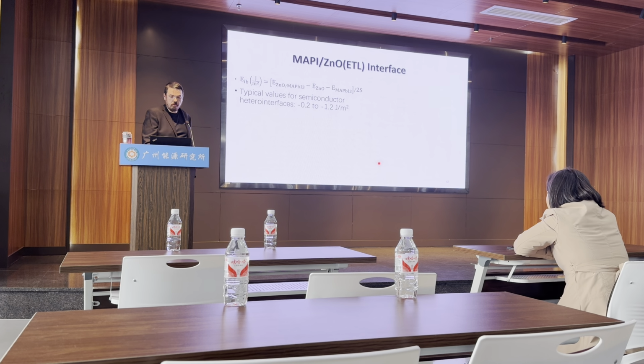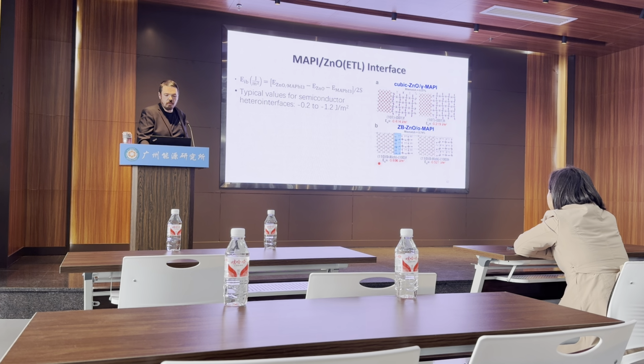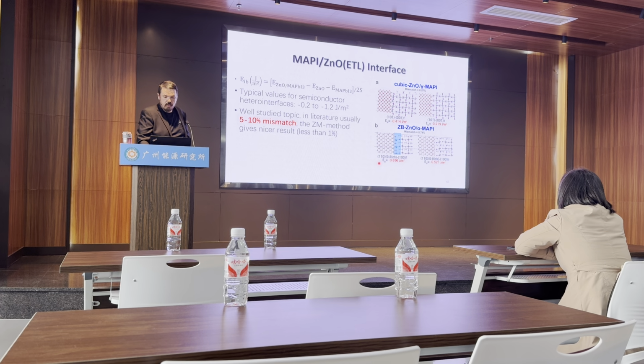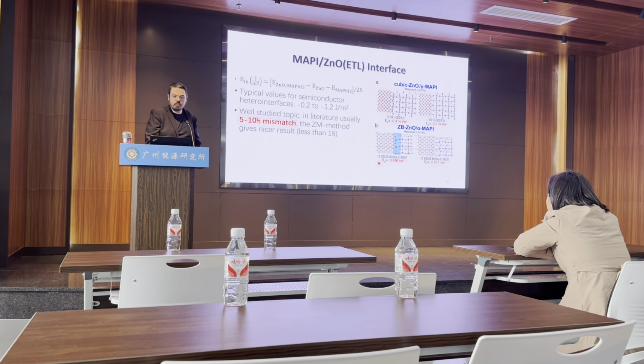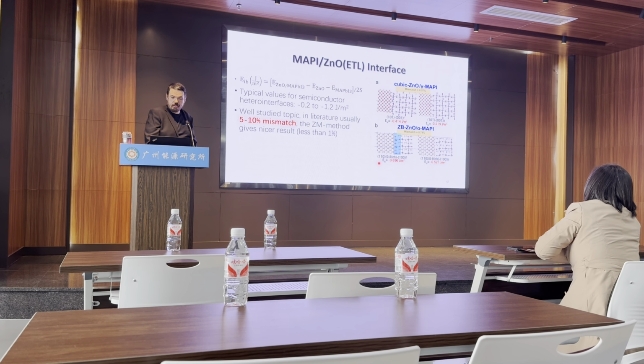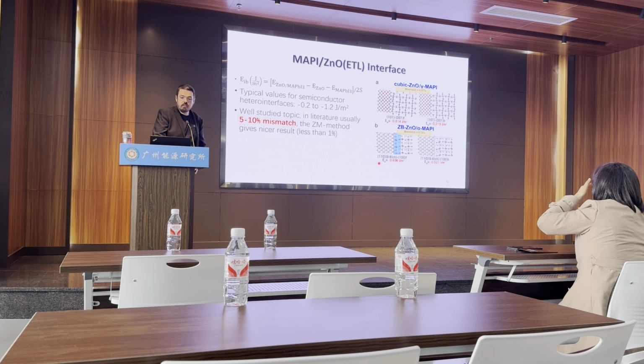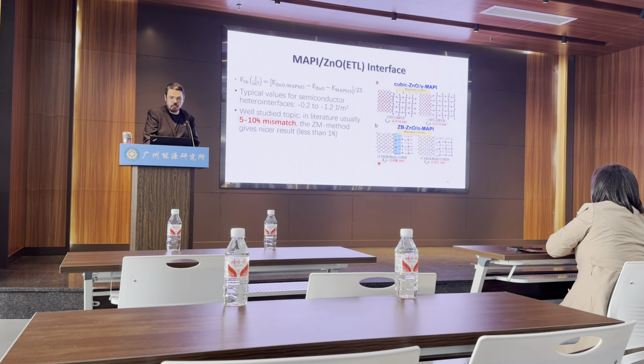So, first of all, before we do anything else, we need to get a stable interface. Typical values of the interface binding energy are from 0.2 to 1.2 joules per meter squared. This is a very well studied topic actually. Many people have already studied it, so it's a bit tough to get into it. Generally, they get 5 to 10% mismatch, and when we look at our numbers, we get less than 1% mismatch. So the two interfaces we proposed are superior to the ones known in literature.